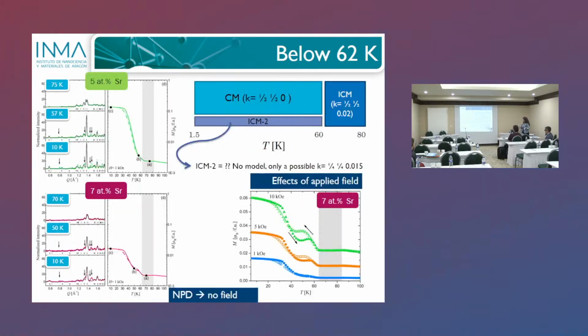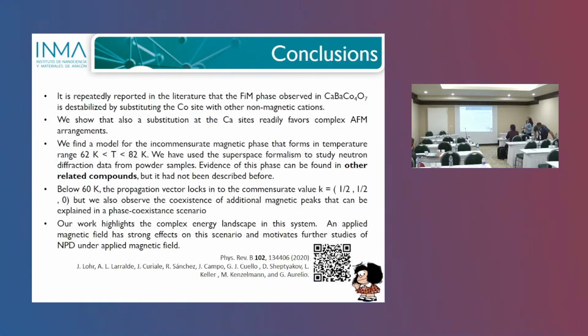So to sum up, it had been repeatedly reported in the literature the effects of doping and the destabilization of this ferrimagnetic phase by substituting mostly the cobalt site, but not other sites in the structure. So we present results for the substitution at the calcium site. The strontium addition really favors complex antiferromagnetic arrangements. We proposed a model for this incommensurate phase. And we also propose a scenario at low temperatures where there are two phases in coexistence, two competing phases. One is the 1/2, 1/2, 0 phase, but we also observe additional peaks that can't be accounted for by these models. And this highlights a very complex energy landscape and the possible role that magnetic field could have on this balance of phases. And thank you for your attention.